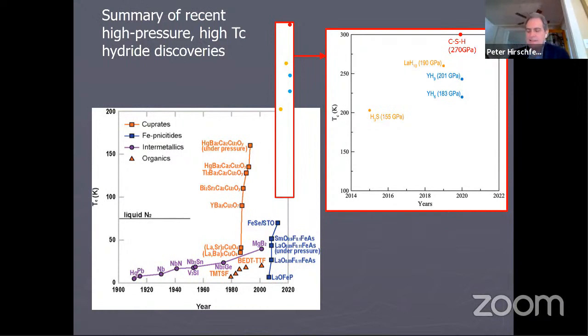So I said that the ab initio calculations predicted superconductivity in hydrogen sulfide. The predictions were within 10 or 20 degrees of 200 Kelvin. And so I consider that to be a big success, if all of it is correct on the theory and the experimental side.